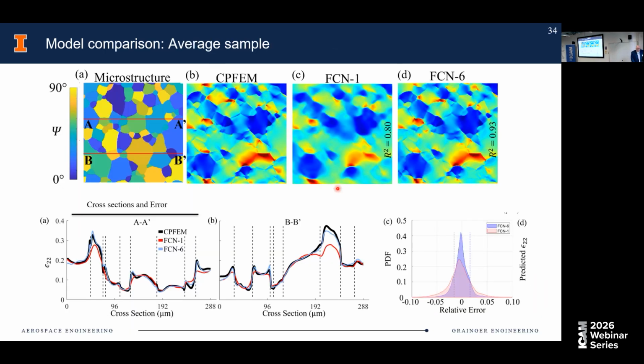So let me skip some of these. So why is this important? Because what we want to pick up is hotspots, places where strain is maximum. And for me, this is what convinced me that this is a useful path to follow. Looking at what would be an average sample, this is the microstructure. This is the ground truth, which is the crystal plasticity result. And this is the prediction of the first and the 6th network, the one that combines everything together.